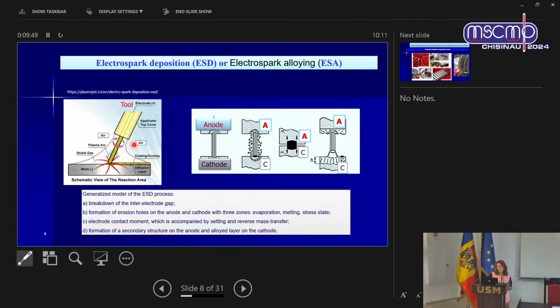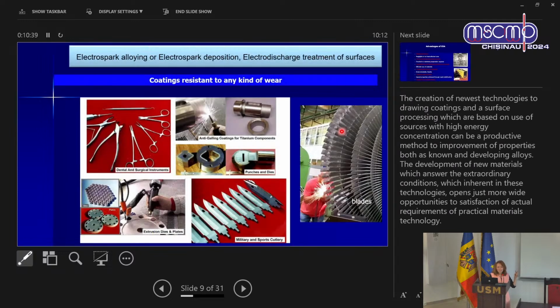Very briefly, to describe what is inside of this process. So you have anode and cathode. And during these short pulses, you have a breakdown of the interelectrode gap. After this, you have erosion hole formation with different types of zones. Here you see evaporation, melting, solid state, sorry. And after this, you have mass transfer between them when they are in short contact. And after this, you already have some deposited material on the cathode workpiece and some material left from the tool electrode.